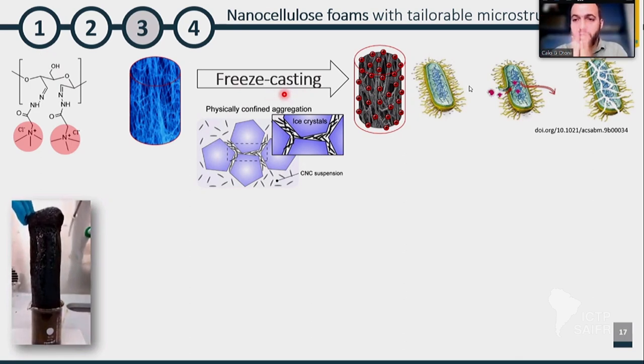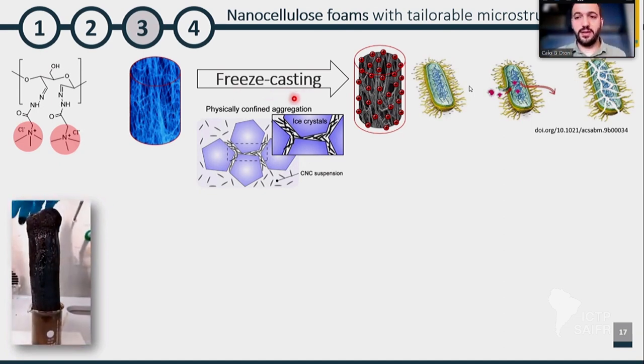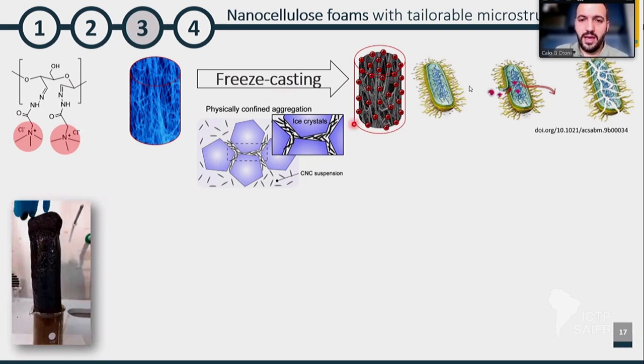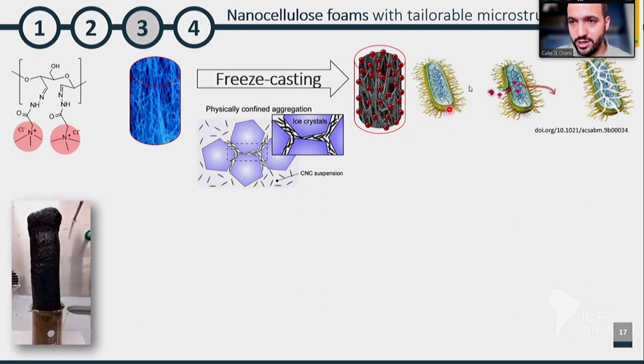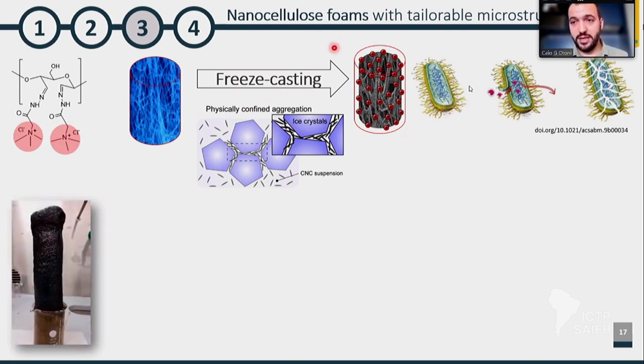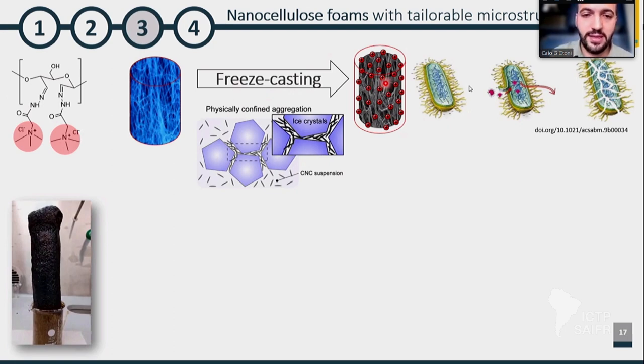confining the particles, the solids, right? And then the ice melts or gets sublimed, gets lyophilized. And we end up with a dry foam that is positively charged because of the groups that are introduced in cellulose, right? And they're really efficient in inhibiting microbial growth, in inactivating bacterial cells that are negatively charged, right? So these foams were basically made for biocidal applications, not only because of COVID, but even before COVID, and it's still ongoing.